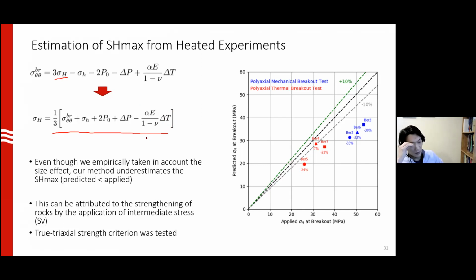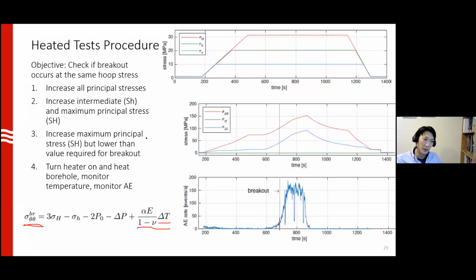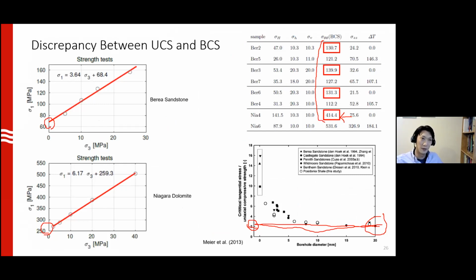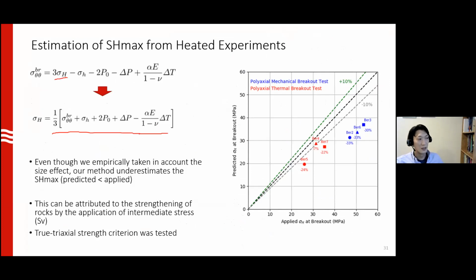So this is where we also run into another big problem. I said that we can empirically address the size effect by saying that even though these hoop stress values do not agree with the UCS that we measure from cylindrical samples, this is whatever stress it takes to create a breakout in a borehole. Even if we take that empirical approach, what we find is that we tend to underestimate the far field SHmax. We know exactly what stress we applied. Sorry, it's on the horizontal axis. We know exactly what we applied, but what we predict from our lab results tend to underestimate the SHmax that is applied.